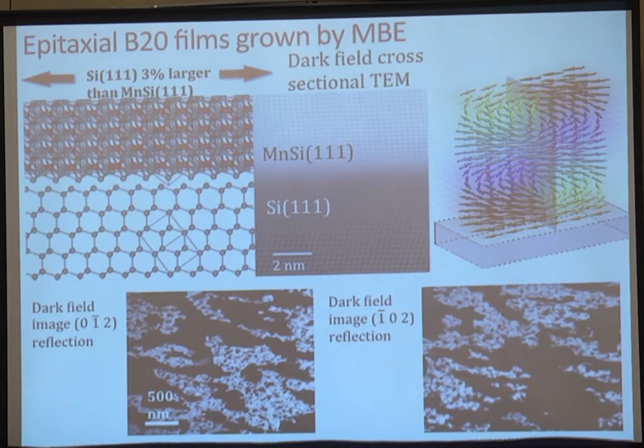What that means is if you have both left-handed and right-handed grains, your magnetic structure is also going to have left-handed helices and right-handed helices. We spent a great amount of time proving that in the zero field state, the propagation vector for the helix points out of the plane. This is disputed, but we have three independent measurements that confirm this, so we're quite confident that this is the case. But at the grain boundary, you can expect a lot of magnetic frustration, and this complicates the situation. It's probably one of the reasons why there's disagreement between various groups about just what is exactly going on.